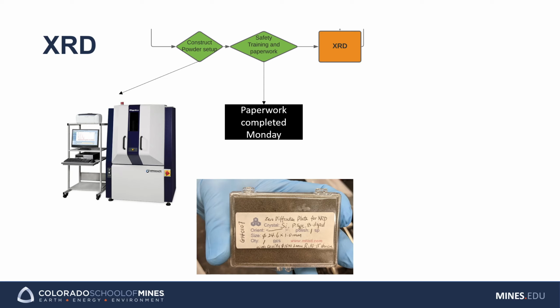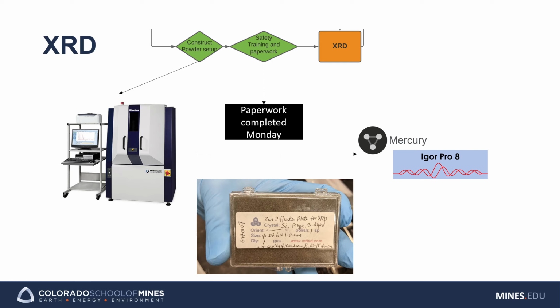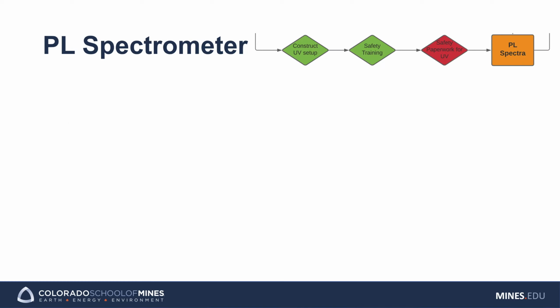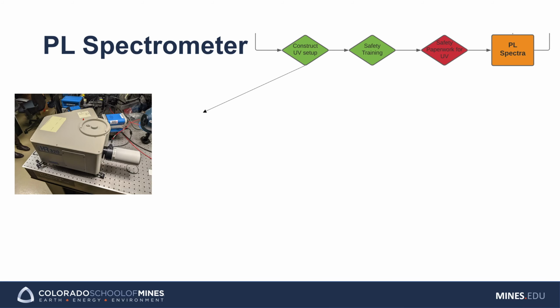So we've got a ton of these little zero diffraction plates to be able to do powder measurements on. Basically, they're just these little silicon plates that we can just throw our powders on and not worry about any sort of background. And then we're just going to do some basic purity analysis using Mercury and Igor just to make sure that we made what we want to make. For PL spectrometry, we had a very similar story as XRD where we had to build out our own setup. We did have a PL spectrometer that we could use, but it did not have a UV setup.